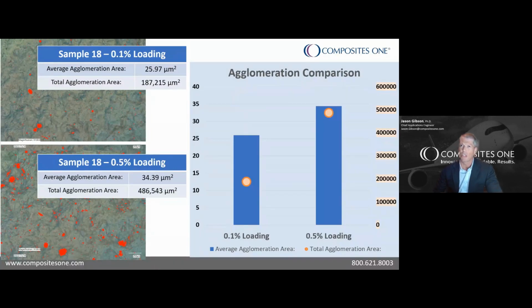You'll notice that not only were there more groups of agglomerations, but the average size of each was higher for that 0.5% loading on the bottom there. And I graphed both the average size and the total area on the right for quick reference. You'll notice a significant difference in both values for each loading level. Now, this information is not conclusive as to why the 0.5% loading did not perform as well, but it does lead us to want to analyze the failure mode via SEM to see if the failure modes of the samples correlate with and originate from the agglomerations or just the particles themselves. Nonetheless, we need to dig deeper to understand why it didn't happen.